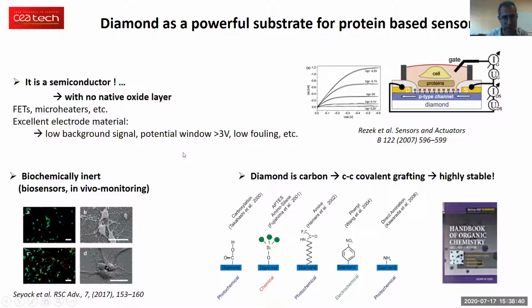Diamond is also a great electrode. It's the electrode that has the widest potential window in water. It has a low capacitive behavior, so it's a fantastic electrode for electrochemists. We can immobilize proteins and do a lot of electrochemistry on them. And it's also a biocompatible material. In fact, besides all this work that we are doing on chemical sensors, we are also working on diamonds for biomedical implants. And in this context, we did a lot of biocompatibility studies, and we demonstrated that this diamond is biocompatible. So cells are very happy to grow on diamond and so on.